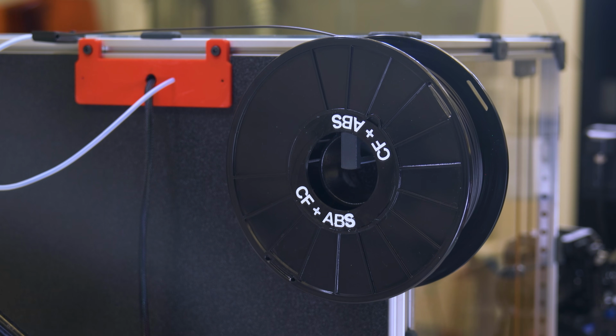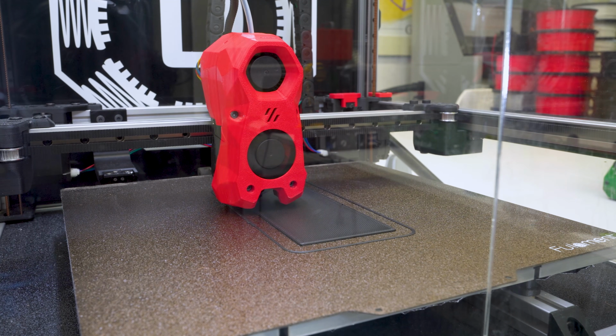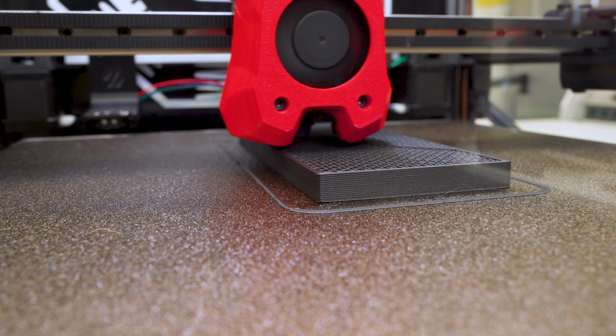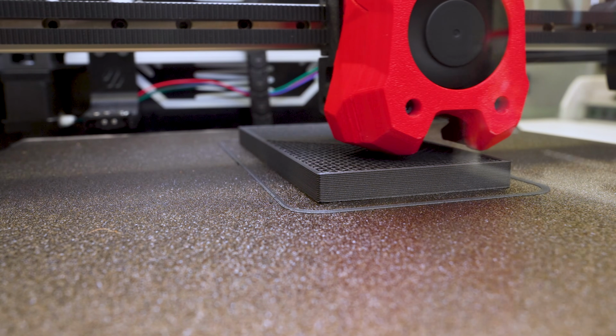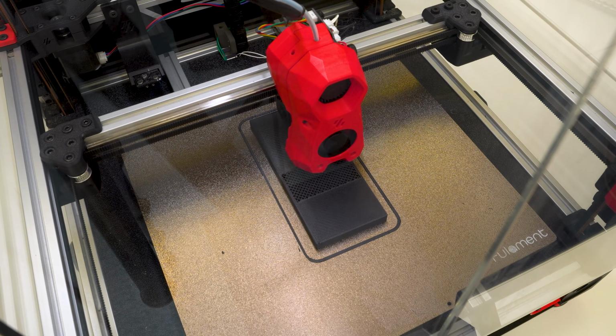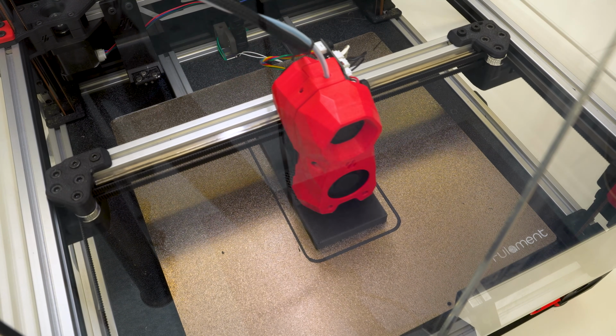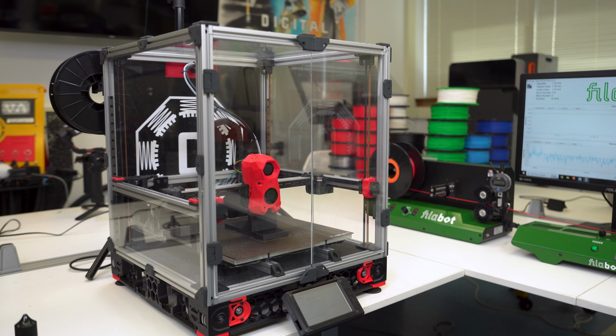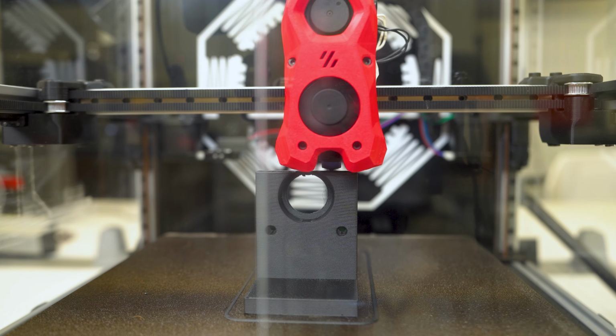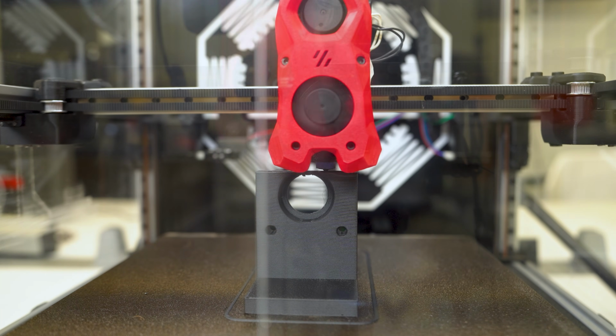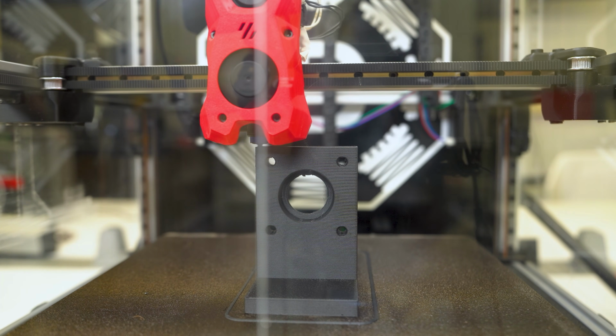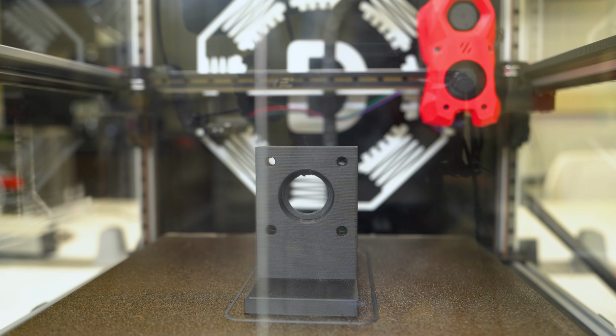Here I have one of my Vorons printing a motor mount out of the carbon fiber reinforced spool that you just saw. I used normal ABS settings but achieved less warping, stiffer parts, and a nice matte finish with this filament. You do have to be careful as the filament can be brittle, so a reverse Bowden tube and a straight path to the extruder is necessary. But with those benefits and a cost close to buying a PLA spool off of Amazon, it's very difficult for me to not print with this material all the time.